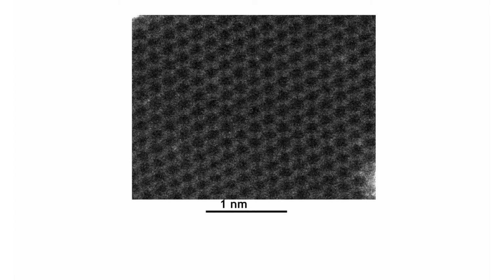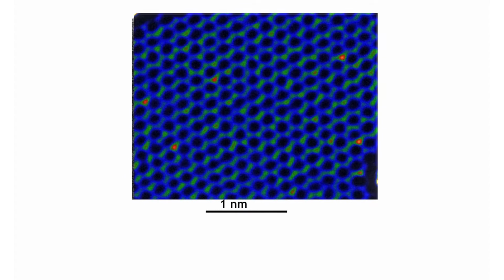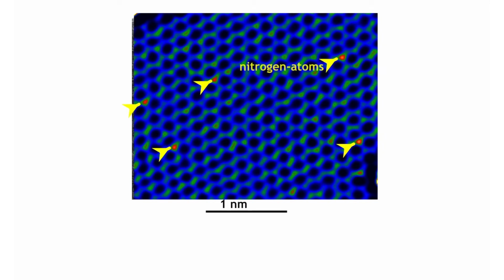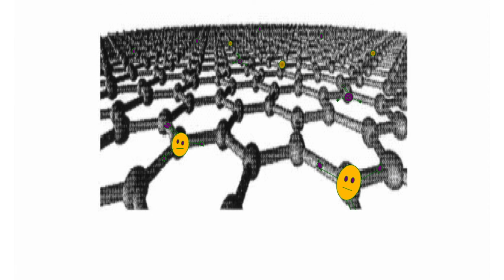So here is again our graphene, and if you look at it, I'll show it in detail now, there are red atoms in the middle of the blue and green graphene atoms, and they are nitrogen atoms. And this was found by electron energy loss spectroscopy, and we have done this on purpose. We have put nitrogen in. We wanted to dope and functionalize graphene. We didn't know whether it would work. And lo and behold, we could see they are there, exactly where we wanted to put them. And this is the first.